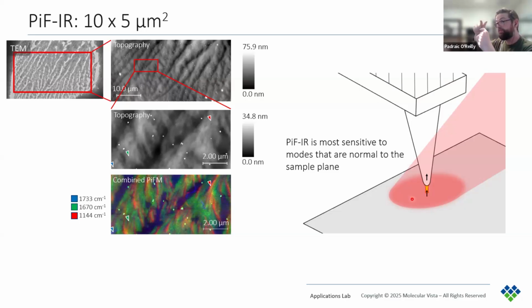So when you have that frequency mixing between the tapping of the cantilever and the IR laser coming in, basically the PiFM signal will only occur when they're right beside each other. So essentially that's exactly where we're measuring the PiFM response, whereas for the topography we're doing the larger area of the tip itself. So we have effectively a smaller tip size for PiFM.